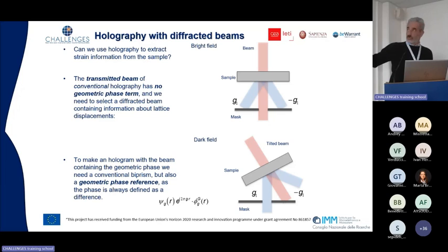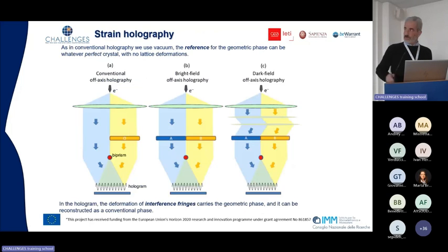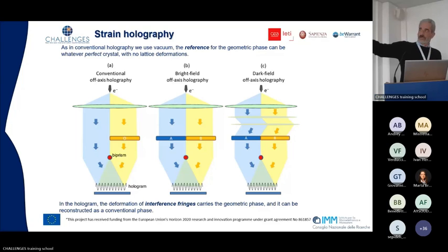The only thing we have to do is now not look at our sample in this position but tilt the beam, not the sample. This is not a good example. So by tilting the beam, so putting on axis the diffracted beam of our sample. This is quite a more clear situation. This is a conventional off-axis holography.